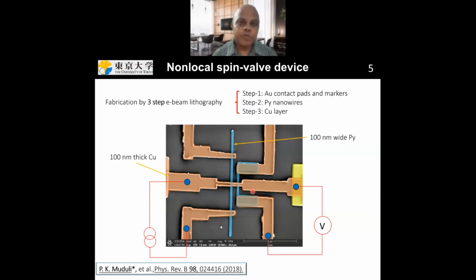So let me introduce what a non-local spin-valve device is. The non-local spin-valve device looks something like this. This is a picture of a non-local spin-valve device. This device was fabricated by me using 3 different steps of electron beam lithography. In this device, you can see there is a nanowire of ferromagnet, this blue line over here. These are 2 ferromagnetic nanowires, and this is bridged by this non-magnetic copper nanowire. So in this device, you can create a spin current and also detect spin current. Let me explain how you can do that.